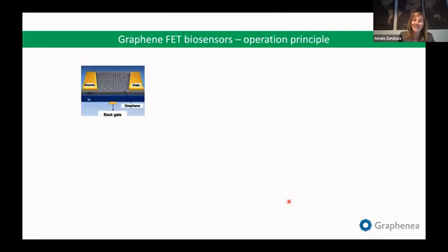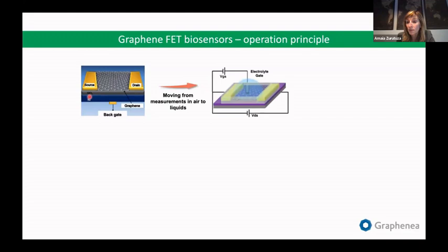Okay, so if we take a conventional transistor, where we have source-drain metal contacts, we typically use a back gate, and this is typically doped silicon. But what happens in a graphene FET biosensor? We move from measurements in air to measurements in liquid, right? So we move from a back gate to an electrolyte gate, because we want to detect biomarkers that are in solution, right?